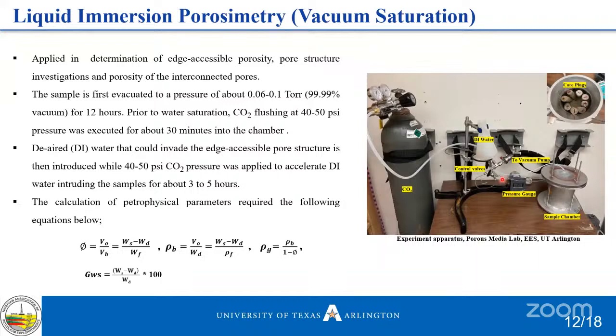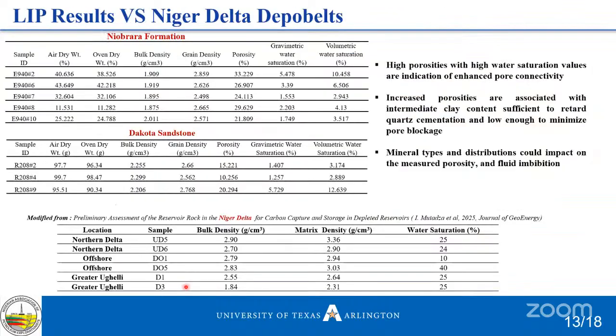Why I'm saying this is because I'm not just making a presentation in terms of academic research, but of applicability in the industry. And these are the equations that were used to determine porosity, grain density, bulk density, and gravimetric water saturation. What you have here is a result of the previous experiment description. For different samples, we have all this information. We computed the bulk and grain density and the porosity. With that, we computed the gravimetric water saturation, which was multiplied by the bulk density to get the volumetric water saturation. And this was also compared with Niger Delta studies for carbon capture and storage in depleted reservoirs.